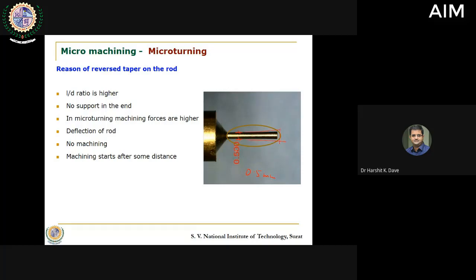The main reason behind this is because it is a cantilever type of structure. So for a particular combination of speed, feed and depth of cut, probably because of no support at the end, maybe deflection occurred more over there. So here, if this is the workpiece, and this is how the tool is placed, then because of the deflection, it did not result in suitable machining. However, in most of the cases under similar situation, this micro shaft breaks. But in one particular case, somehow it did not break, and we observed that a sort of reverse taper occurs. So even though the tool might be coming into contact with the workpiece, it may not be resulting in proper machining. And so that may be the reason.